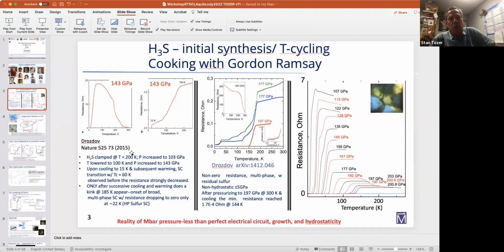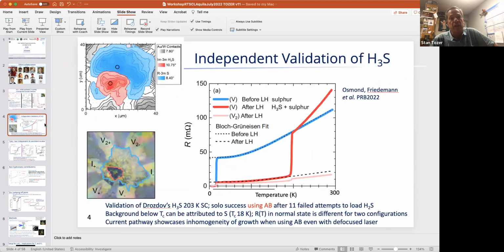And it just points to how difficult these measurements are, both defining an electrical circuit, getting a sample to grow, and hydrostatic conditions. They're typically plus minus 5 GPa, which isn't a lot when you're up at 140 GPa, but it's still there. It strains the sample, and that leads to broadening of the transition, as I'll show shortly.